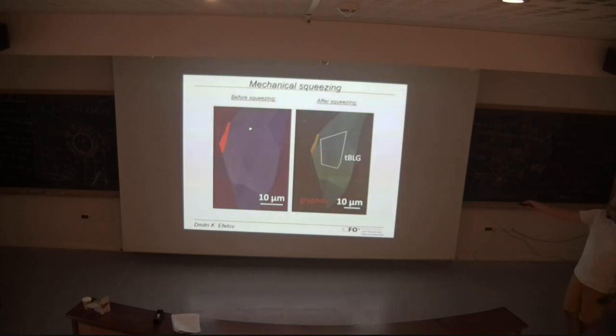And as you can see, there are a lot of bubbles initially when we make these. And we basically found a way to squeeze these bubbles out. We found a way to release the stress and strain within the system. We were able to remove these strain centers, and we ended up with a bubble-free device architecture.